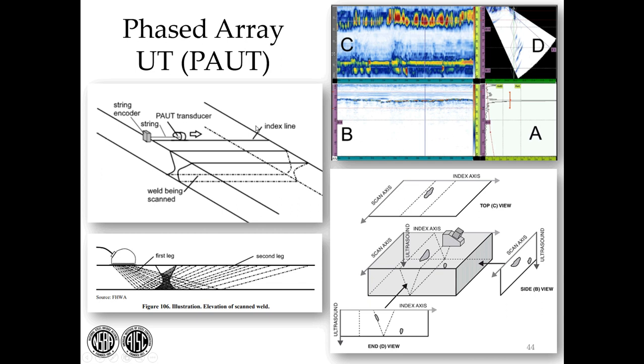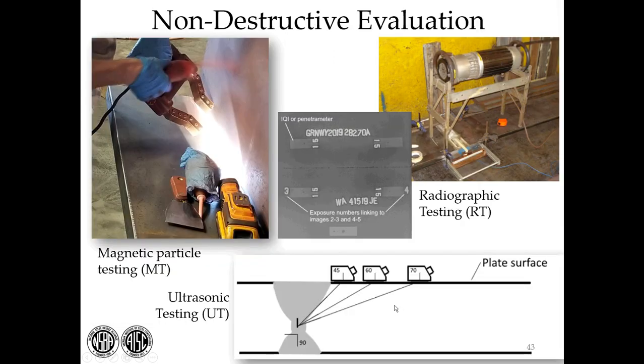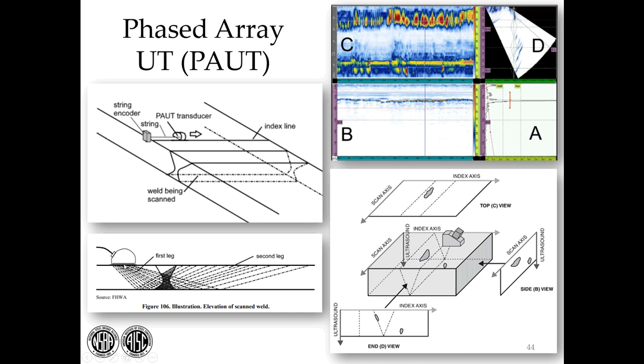So newer technology coming into fabrication is phased array UT. With phased array UT, instead of one sound path, multiple sound paths are sent, and they're sent at multiple angles. So at this one position, this amount of weld can be seen. If you think about a UT, in order to scan the entire weld, you'd have to move this probe back and forth, and that's what technicians do. With phased array, in one position, you can get most of the weld.